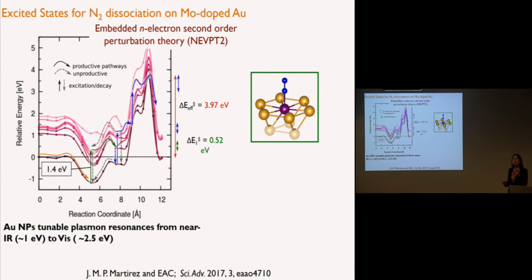So for sure, what one sees, and that's also part of why the yield is low, is that these processes do in fact require multiple excitation events. So this is modeling that multiple excitation event. We envision something where it can be promoted up to this excited state, and then it can undergo a barrier that's only half an electron volt, almost an order of magnitude less. And it can then traverse that thermally at room temperature.